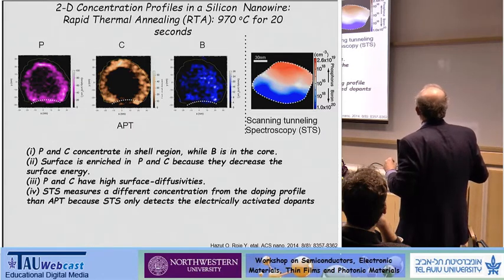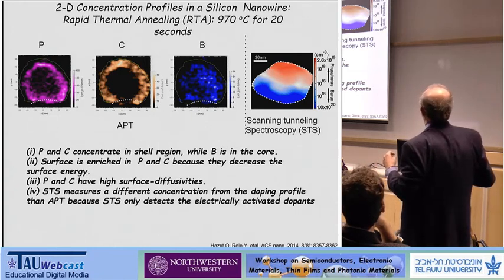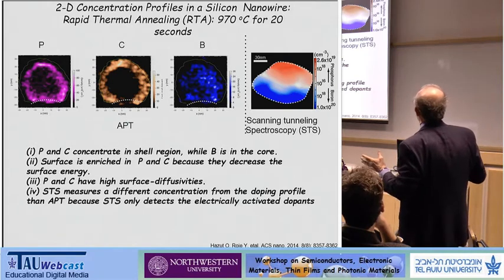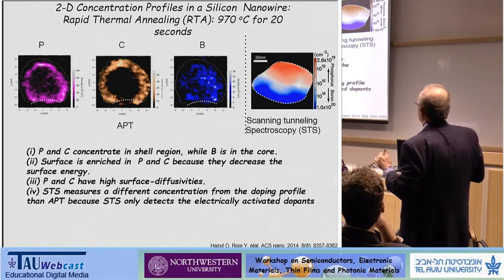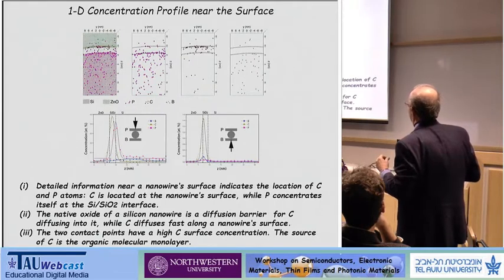Now, if you look over here, this is a scanning tunneling spectroscopy image, and you'll see it looks different from the atom probe tomographic results. The reason is that in the atom probe tomographic results, we see both the electrically active and the electrically inactive dopants, whereas in scanning tunneling spectroscopy, we only see the electrically active dopants. So you can see there's a significant difference between what you get from the APT and what you get from scanning tunneling spectroscopy. Okay, now let's go into a little bit more detail.